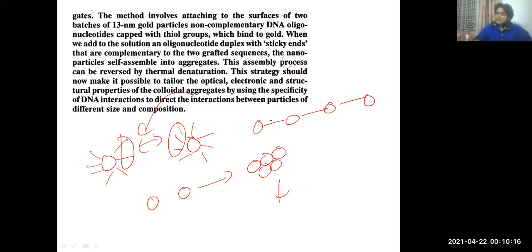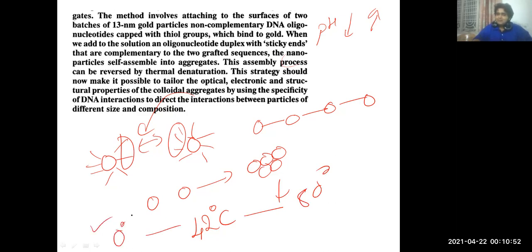Now, since this is by oligomerization, there is also alkaline-based denaturation of DNA, acid-based renaturation. So you decrease the pH, you end up assembling it. You increase the pH, you end up dissociating it. Also with temperature denaturation. Since we are synthesizing these oligonucleotides, there is a formula to calculate the denaturation temperature, which was found to be 42 degrees for our example sequence, which means you take double of this. Let us consider 80 degrees and then go all the way down to 0 degrees. At 0 degrees, they would have assembled. At 80 degrees, they would have disassembled because of denaturation.